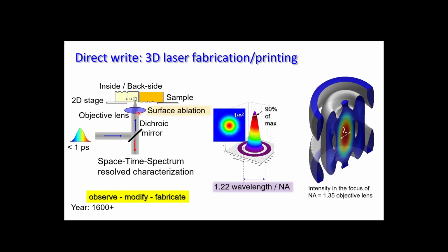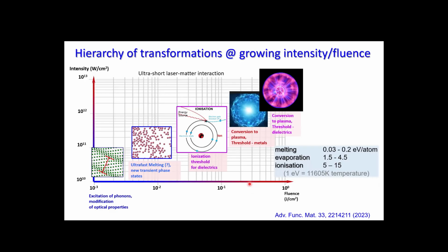And focusing here is nothing fancy. We are focusing to a focal spot size comparable with the wavelength of light, let's say 1 micron in diameter. But the modification which we can create can be localized much better because we are not bound to the diffraction limit. If we modify the material at the very tip of the intensity distribution, we can do better than the wavelength. That's why we are not limited by, and not required to decrease, the wavelength in order to have higher resolution. In terms of material science, this is the perfect tool.